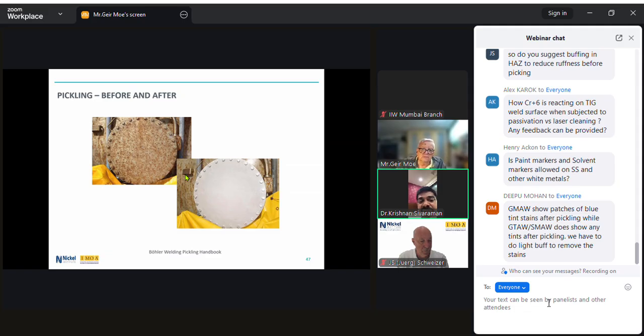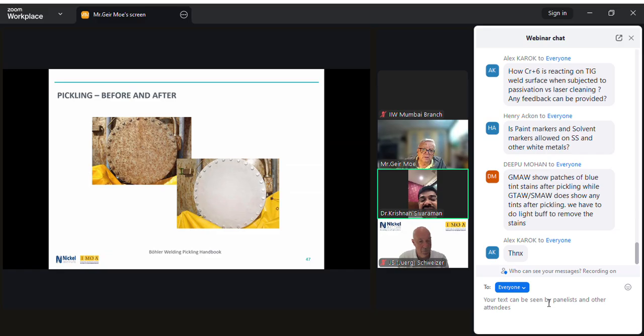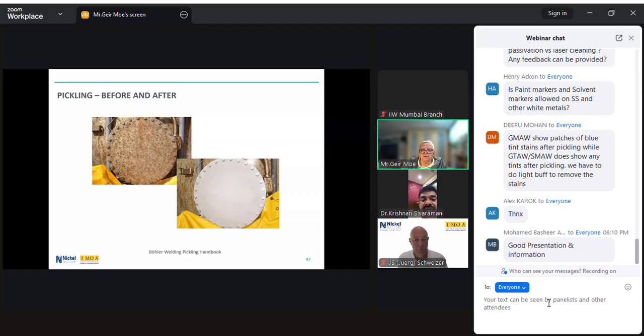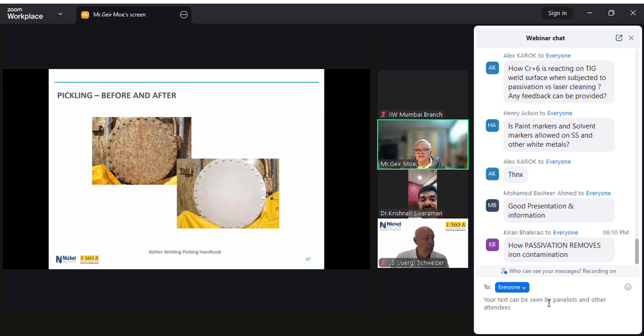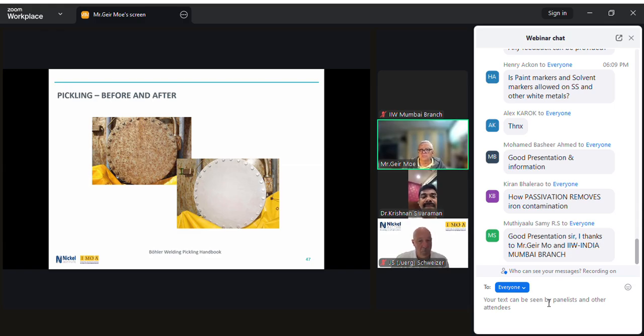There is one interesting question: are paint markers and solvent markers allowed on stainless steel and other white metals? Paint markers, yes. Well, anything on the surface is a contaminant, and if you put that stainless steel into an aqueous corrosion environment, any markers will likely have chloride in them. There is no such thing as a marker that is 100% free of chloride. So if you put that stainless steel into service in an aqueous environment where chloride is present, you could have premature pitting corrosion where the paint marker has been applied. It's just one of the potential contaminants, and it shouldn't be there.